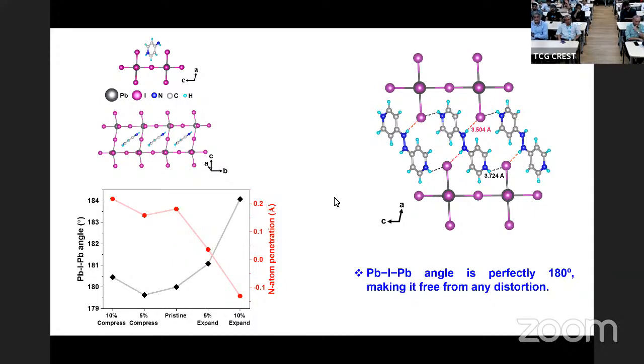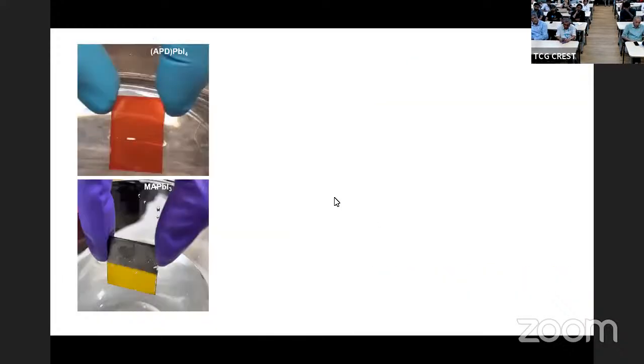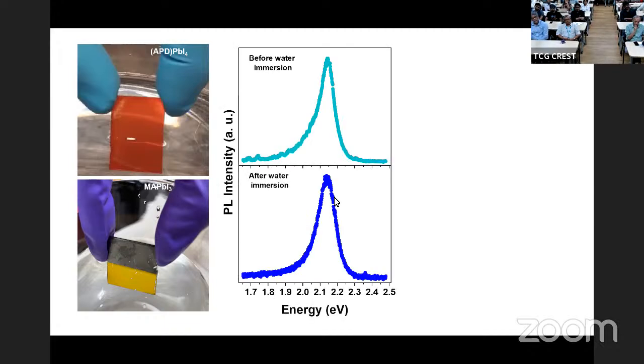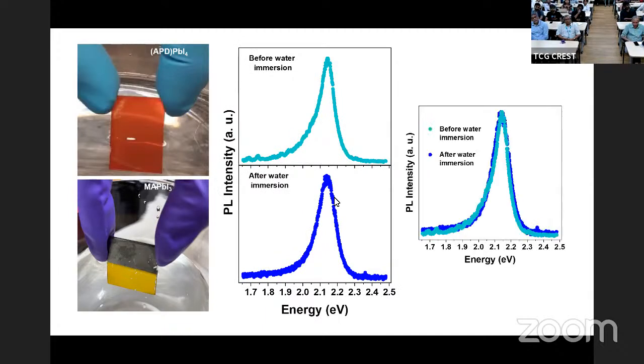Well, I've talked about how we have got the lowest band gap and lowest excitonic binding energy. What about the stability with which I motivated you right in the beginning? It turns out that it's also extremely water stable. This is a MAPbI3 film, which looks black. Dipped in water, you know where the water level is. Within seconds, it turns into PbI2. This is the material that I talked about, APD PbI4, dipped into water. There's absolutely no change. This is, of course, visual, but one can characterize it by looking at the photoluminescence before and after immersion. And to convince the disbeliever, you can see that they're identical. One falls on the other. So it's extremely water stable.